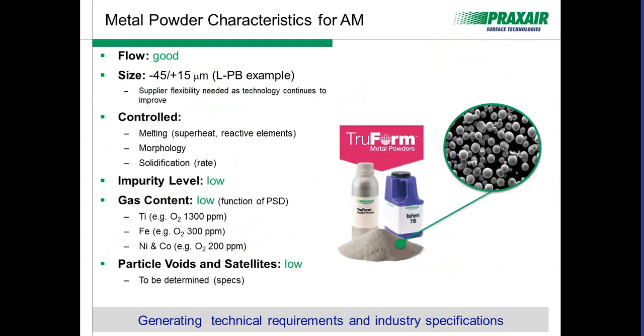As I spoke to earlier, we need to control the morphology. Also, solidification rate. In many cases, we're now seeing customers asking for what we call metastable powders, so powders that are solidified at a rate that can lock in a certain key microstructure that they can't achieve using conventional casting techniques. That's really another advantage of gas atomization. It is truly a rapid solidification process that allows us to achieve a microstructure that can have certain properties that you can't achieve using conventional casting because of its metastable nature.